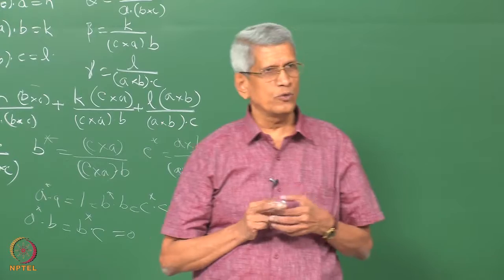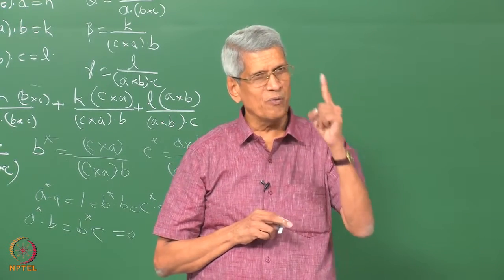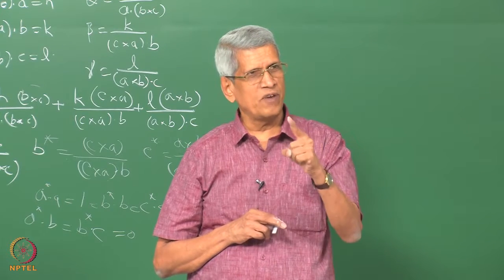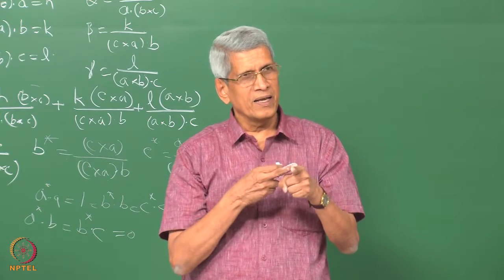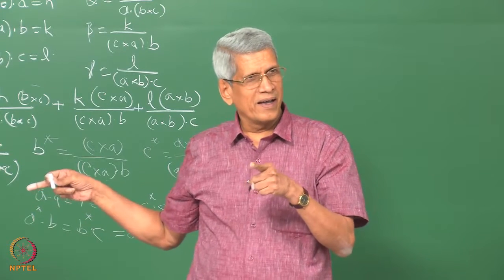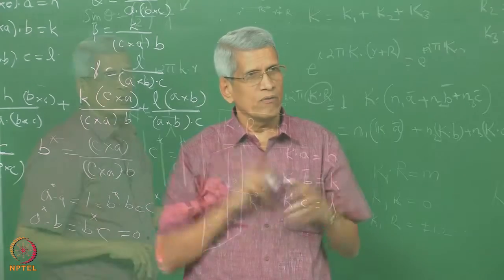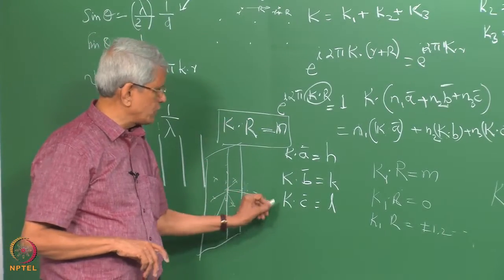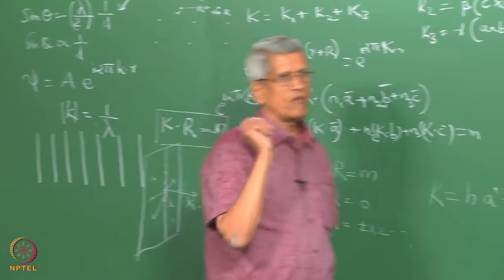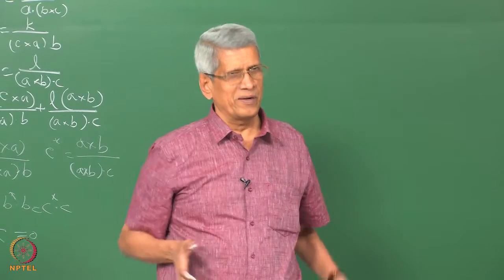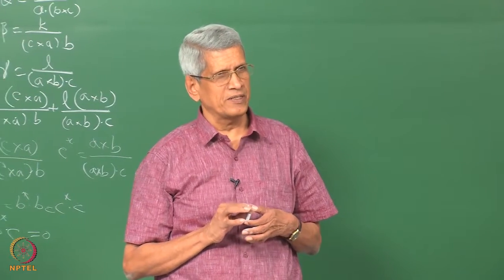All these vectors are perpendicular to that k1. K1 is only one vector in reciprocal space, and to that vector there are many periodic distances. So when k1 dot r equals 0, it means that all the values of r represent a plane which passes through the origin and which is perpendicular to k1. That is the plane which it represents.